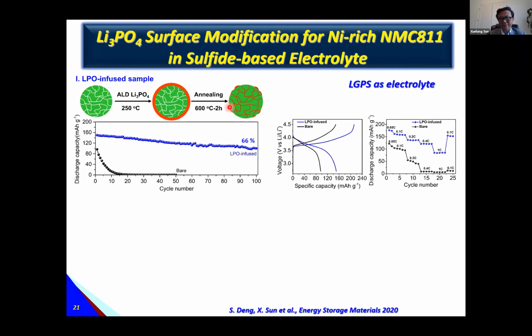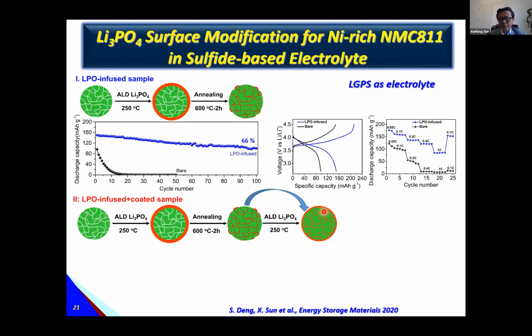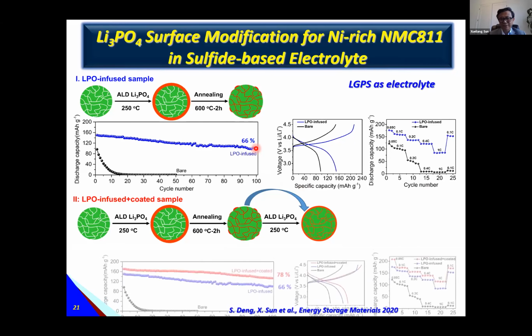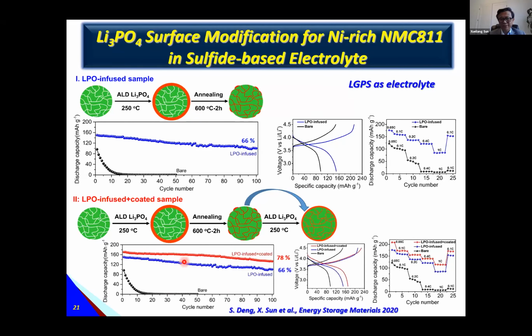So we think about this: after ALD coating and annealing, the material penetrates in, but the outside is exposed. So we think, can we use an extra coating on top to increase capacity retention? After we tried this, with the additional layer coating, capacity retention after 100 cycles increased to 78%. And repeatability also increased.